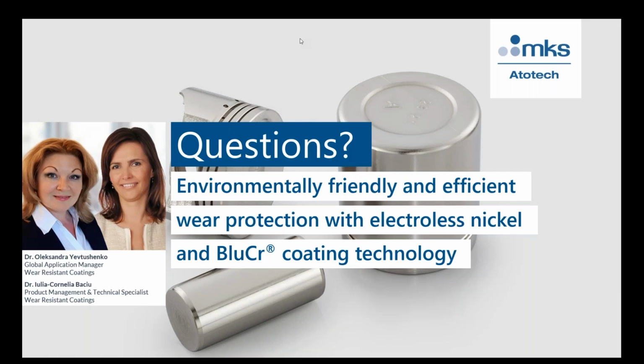Thank you, Julia. We have a similar question, but this time it's in regards to BluCr. Why is hardness increased during the heat treatment in regards to BluCr? Okay. As I mentioned already, the BluCr layer itself, the chromium layer, contains carbon, and the carbon will build up chromium carbide phases. There are a lot of different phases, and depending on the temperature you apply, starting from 150, 200 degrees C, very slowly the properties of the layer will change. The hardness will increase, the wear resistance will increase, and this is exactly due to these chromium carbide phases which build up at the high temperature.